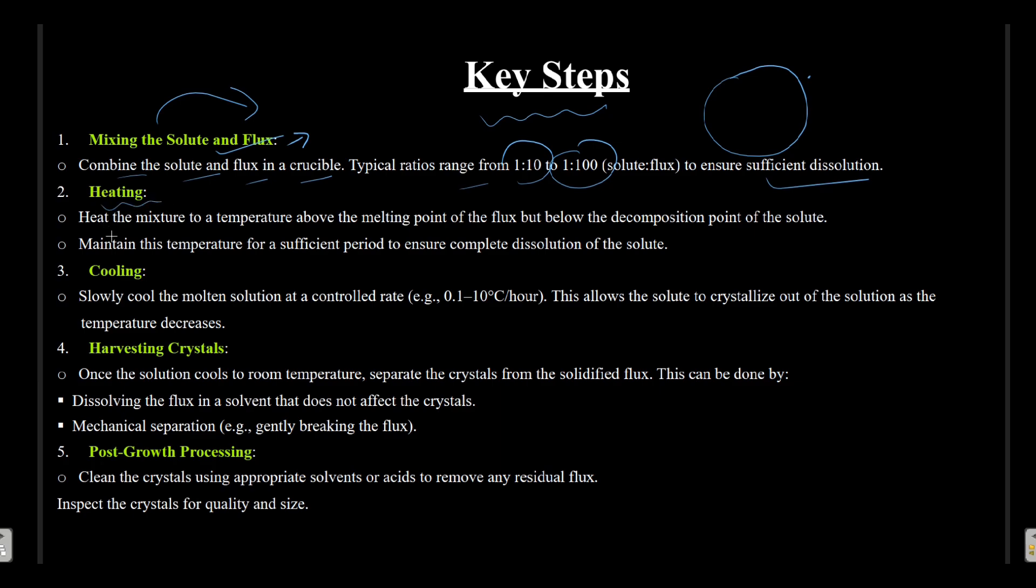Similarly, the second step is heating. So heat the mixture to a temperature above the melting point of the flux, that means the flux should melt, but below the decomposition point of the solute. Solute should not decompose at any further temperature. So the flux should be melted, but it should not be heated to very high temperature where the solute actually gets decomposed.